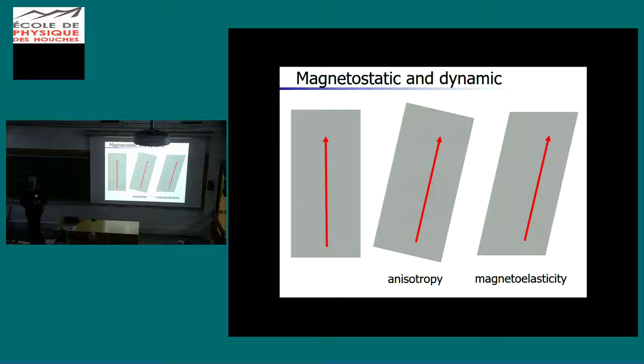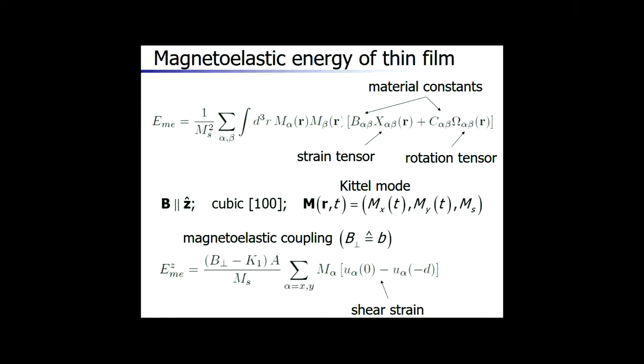Now, so what happens if you have this magnetization dynamics? In an adiabatic limit, the lattice would like to follow the magnetization in order to get the minimum energy conformation. Now, this can do it in two ways. It can either do a local rotation to the magnetization, or it can accommodate this magnetization by a deformation. So these are basically two different independent effects which should be taken into account. Right. And if this precesses, these two are coupled, of course.